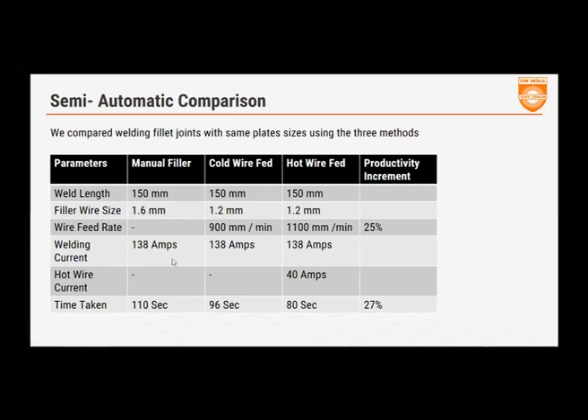Now, we kept the same current range, we kept the same fillet size, and we introduced the cold wire feeder. The welder was feeding the wire at about 900 millimeters a minute. This would be equivalent to the wire volume of 1.6 at this rate. And the welder could complete the job in 96 seconds. This is because the wire was coming on clean to the job, and 1.2 requires a lot less heat to melt than 1.6.